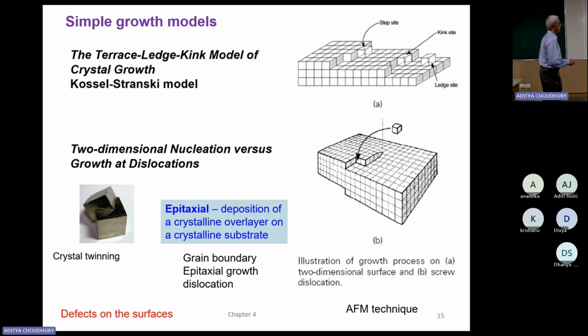The second one is screw dislocation. Its name is screw dislocation. It started growing this way. And again, they have their own mechanism, the way it grows. Sometimes it gets twisted. You start getting twinning, two crystals stuck together, because the free energy of the surface is conducive for the growth of some other crystal. Two crystals will come in contact and they started growing. These two single crystals have completely different planes and started growing here.